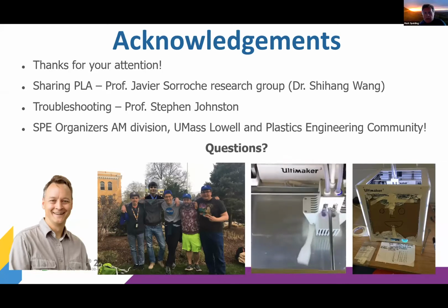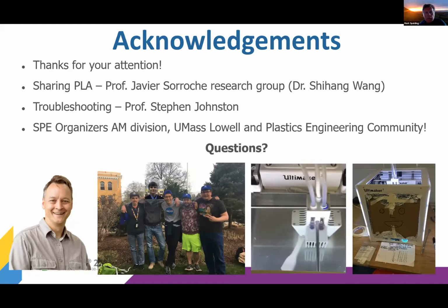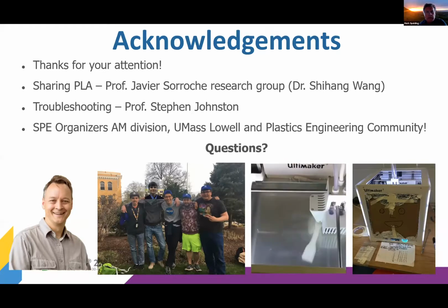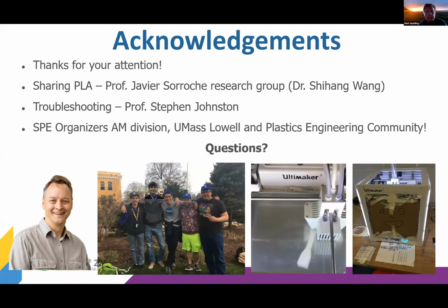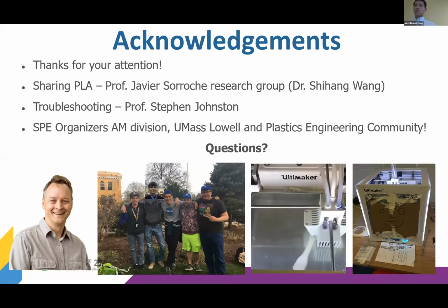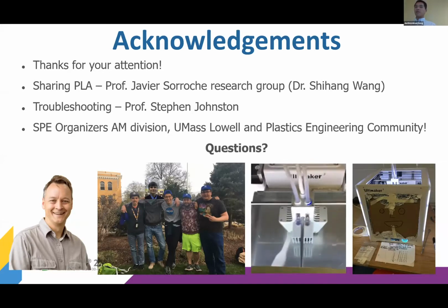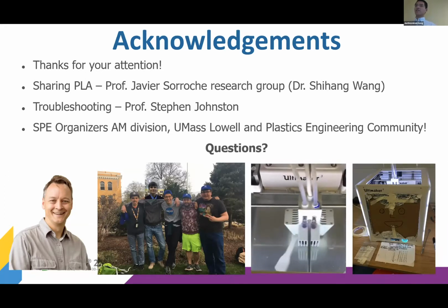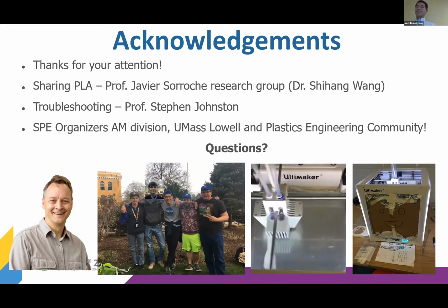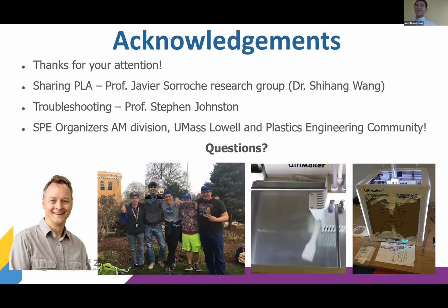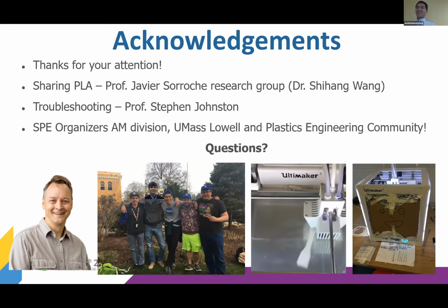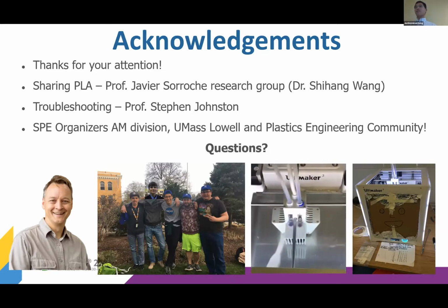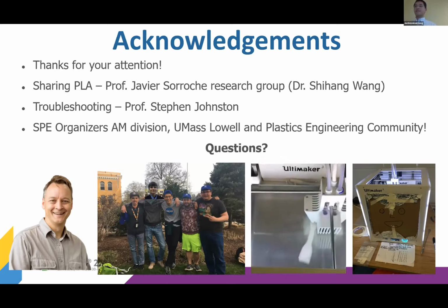I am not a failure expert, but when I looked at some of the breaks on those parts, it looked like there were two different failure mechanisms. Yep. So our larger nozzles typically broke in a brittle manner, while the smaller nozzles, which had better resolution, it was more fibrillar. I'm not sure if those are the right terms for it. It would somehow have a larger strain per se. Okay.